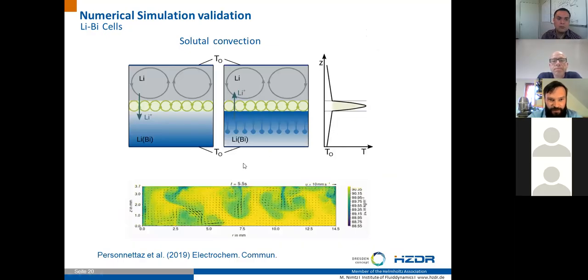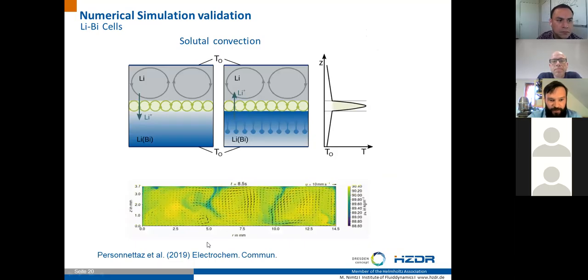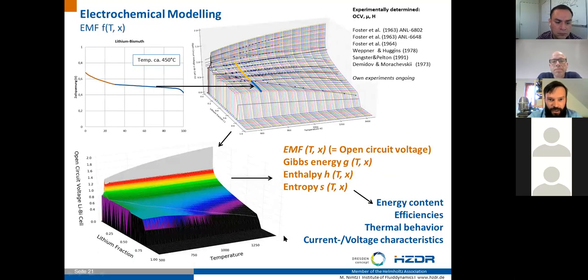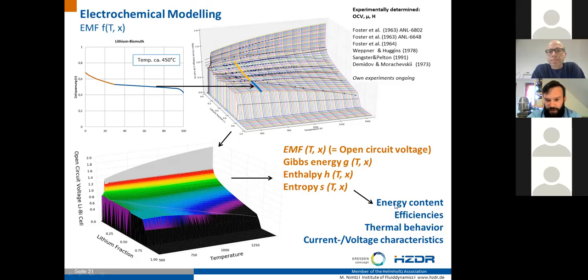Similar experiments were done for solutal convection by Personnettaz, and I've been using these and other experiments to get ideas on the open circuit voltage, which are then used to get voltage models for the whole temperature and composition range. And with such a voltage model, you can also get information about Gibbs energies, enthalpy, entropy, and then use this information to model energy contents, efficiencies, thermal behavior, and in general current and voltage characteristics.